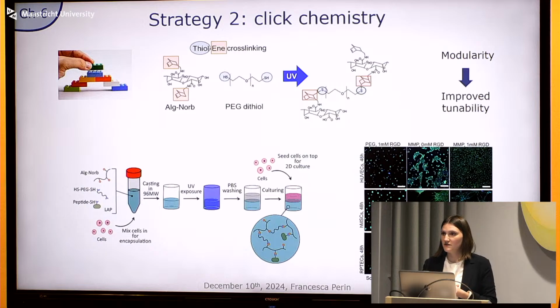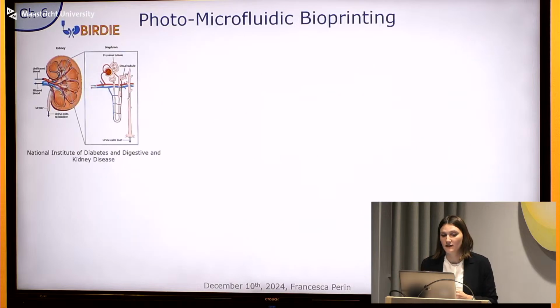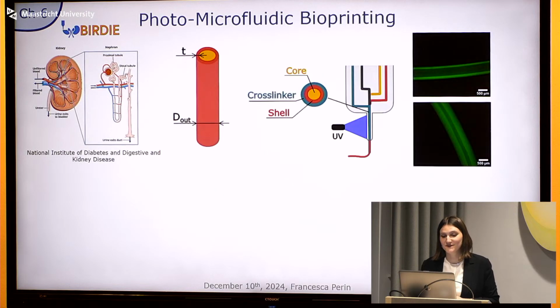So these experiments served us to select the optimal conditions that we needed, and then we could move forward to bioprinting. And for bioprinting, because all this work was carried out under the Birdie project that aims at mimicking in vitro the kidney, in particular the nephron, we were aiming at printing capillaries and tubular structures. And we selected once again to use the microfluidic bioprinter, but this time with a more complex printhead that allowed us to produce hollow fibers by use of a sacrificial core.